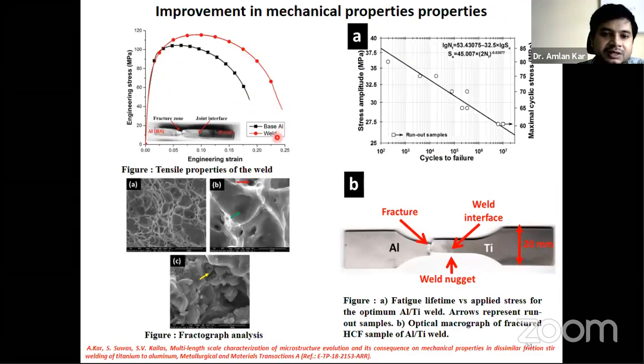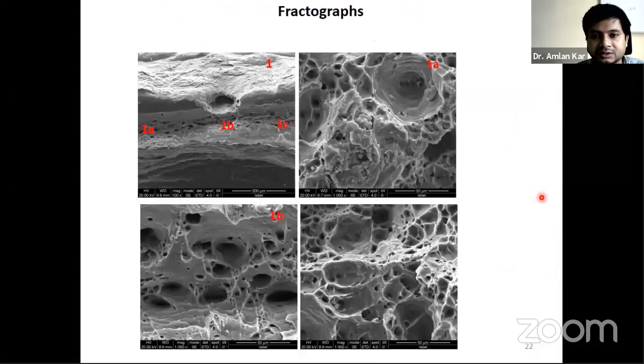You can see very good ductility, and we can see that the fracture location is away from the zone because of the particle distributions. And we have observed very good fatigue property as well. So this is the typical phenomenon we have generally observed in the case of welding.